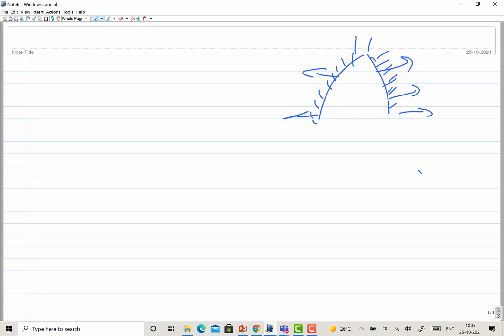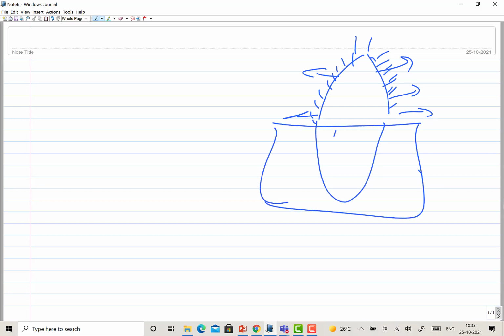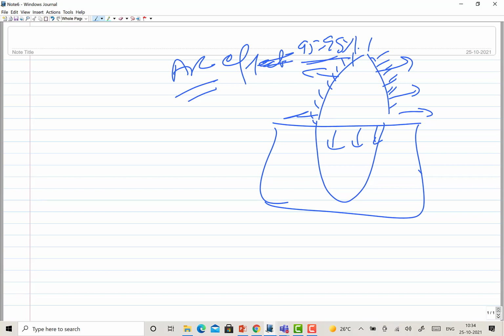So most of the heat generated is used for the melting. So the arc efficiency offered by the SAW process, submerged arc welding process, is like 95 to 99%. Very limited losses of heat will be there from submerged arc welding, while in case of shielded metal arc maybe 70-80%, in TIG it is 40 to 50%, because a lot of heat losses will be happening from the welding arc, and all the arc heat being generated is not used for the fusion and the welding purposes.